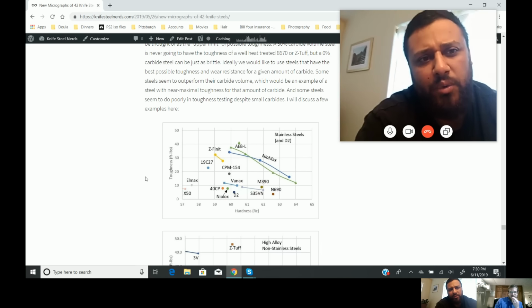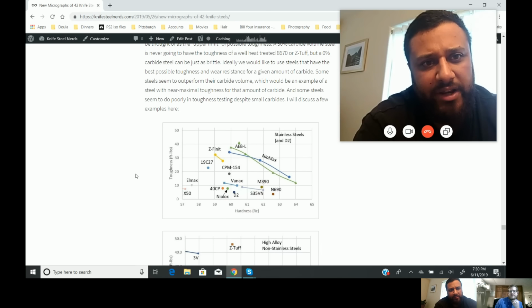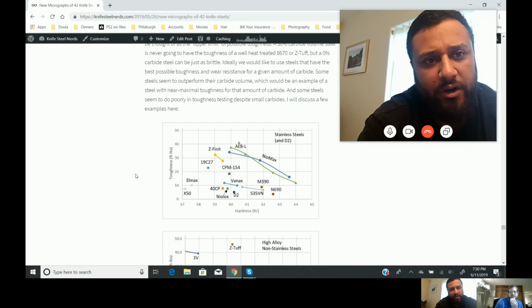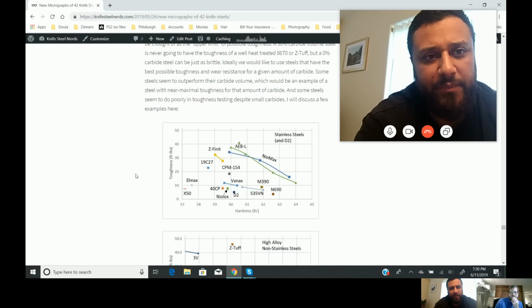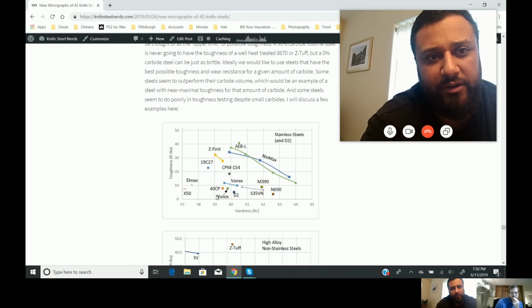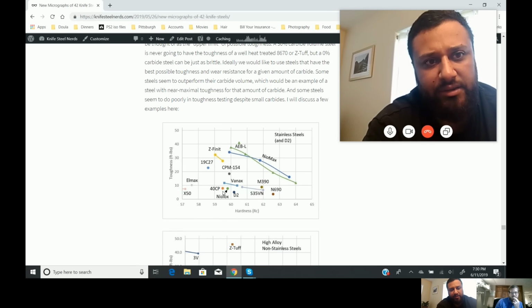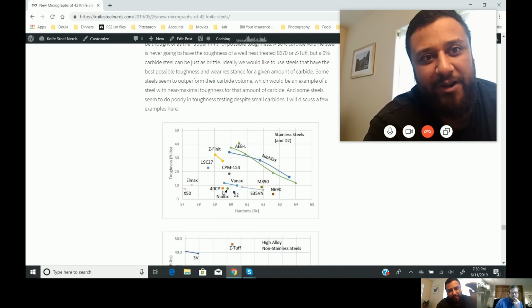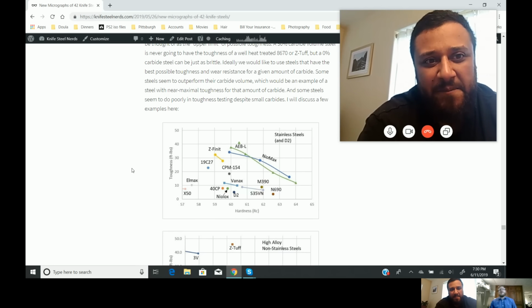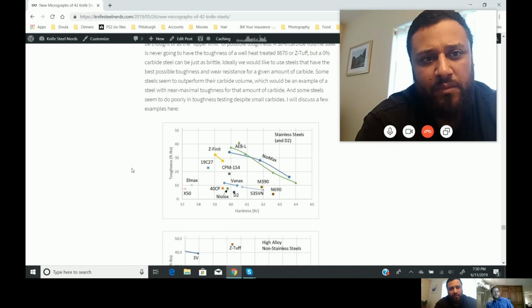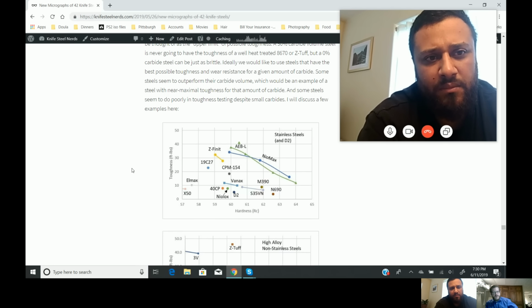Interesting. What's throwing me for a loop here is the fact that we have Elmax, Vanax, and M390, which had the finer looking carbides, and the CPM 154, but that CPM 154 really sticks out. The carbides looked like they were bigger. They didn't have the vanadium and stuff in there. But it looks like that tested tougher. But then we have 40 CP, which also is a very chromium dominant steel, which maybe would look similar to the B75P, B70P, and the CPM 154. But we got CPM 154 like boom up here. Yeah, and that's one of those mysteries. What are the other factors that are playing in here? Why was the CPM 154 tougher? And I don't know the answer.